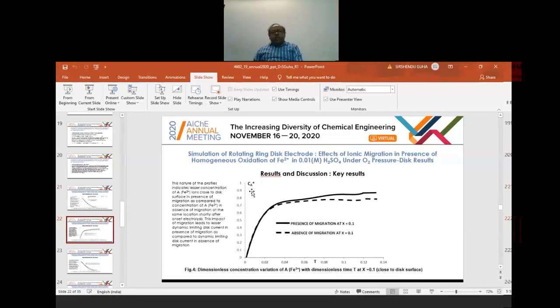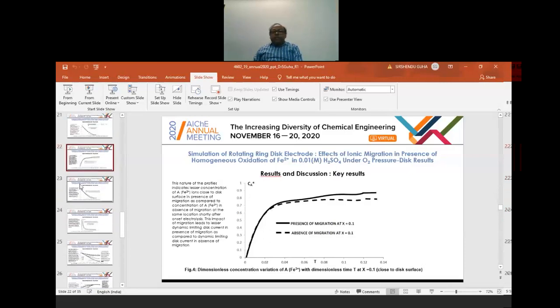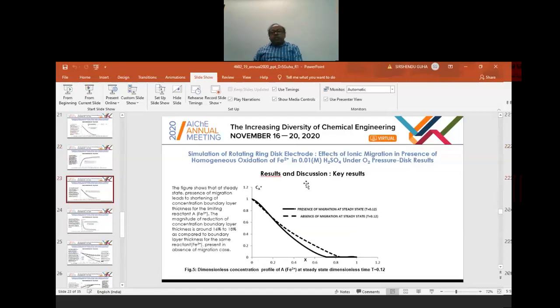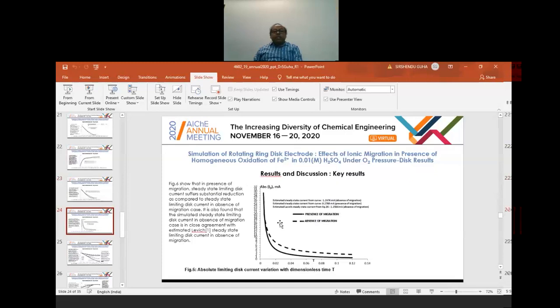Now, in figure 4 the dimensionless concentration of A is plotted with the dimensionless time, and the effect of migration is also visible. That is, the dimensionless concentration of A is always higher from t equal to 0.02 onwards than the dimensionless concentration in absence of migration. So the effect of migration is quite visible. Now, in the next slide, the concentration of A is plotted against the dimensionless normal distance. Here also the effect of migration is quite visible. Now, I will go quickly through these slides because of lack of time.